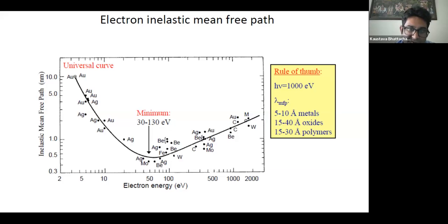But we still require a stronger vacuum in XPS because of another factor, which we call the sticking coefficient. If we think of an atomistically clean surface, in the atmosphere there are mainly nitrogen, oxygen, and moisture. Others I can disregard. The sticking coefficient of oxygen is very high, so oxygen starts building monolayer after monolayer upon the surface. For example, if I'm checking silver, I'll get an extra false peak of oxygen just because of the sticking coefficient of oxygen.